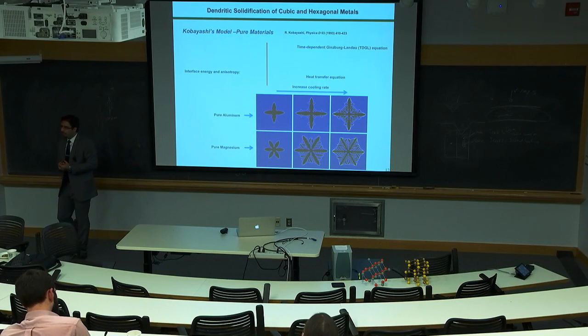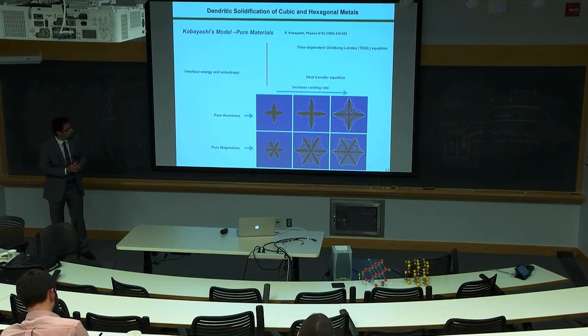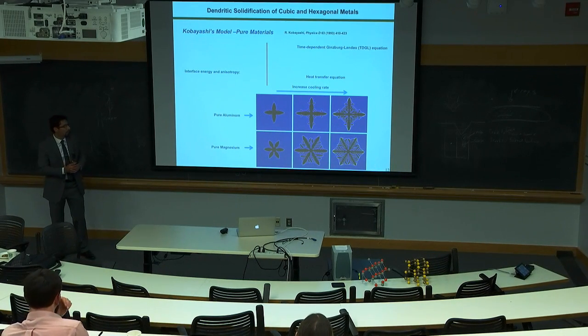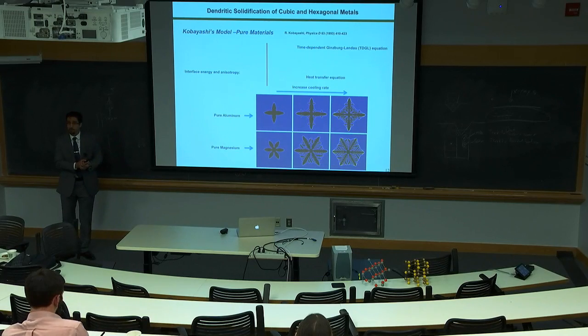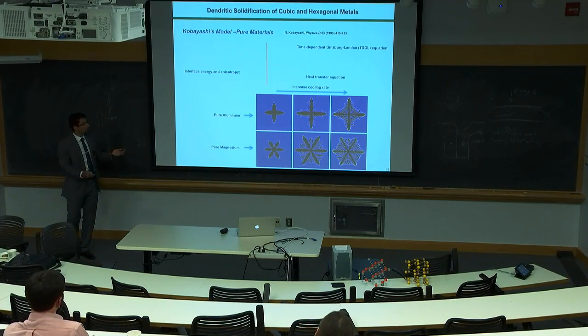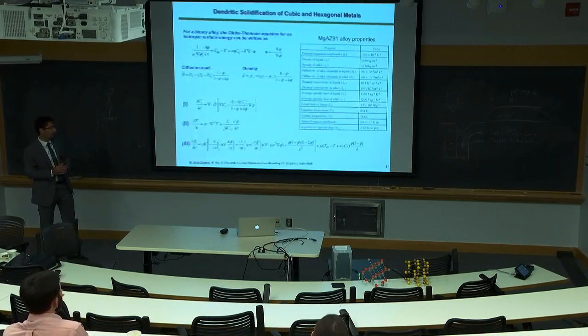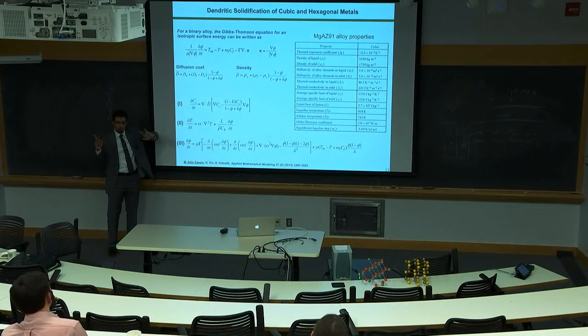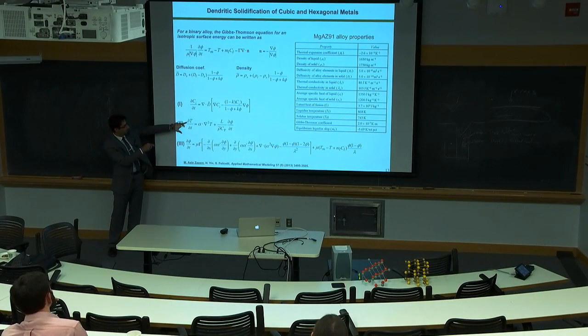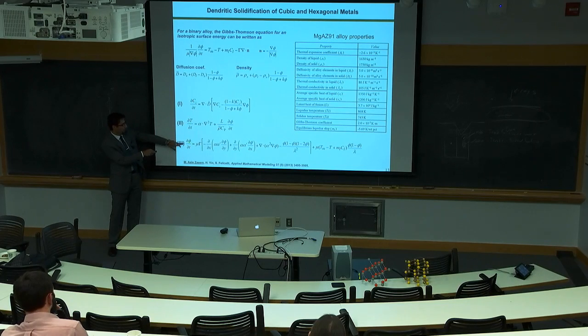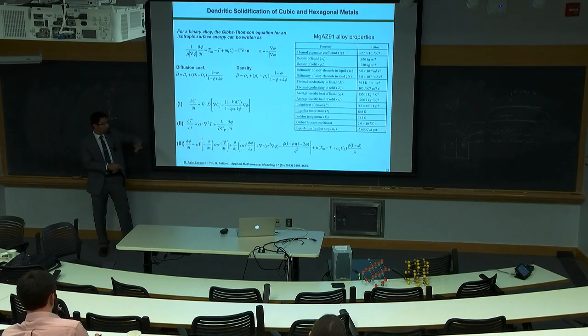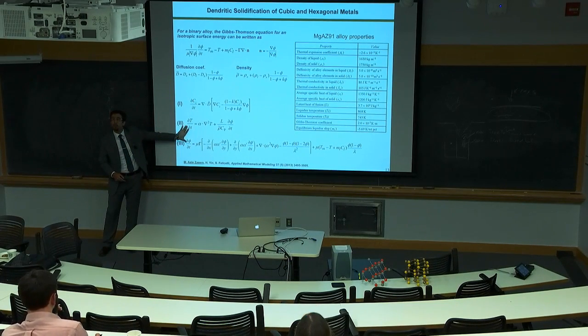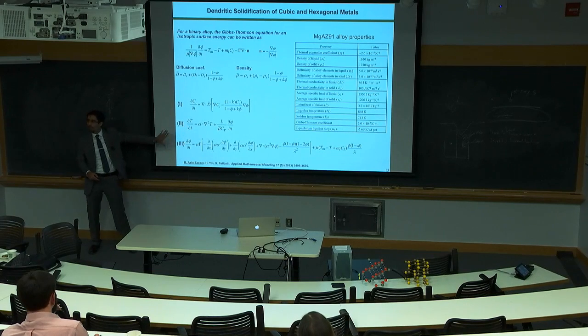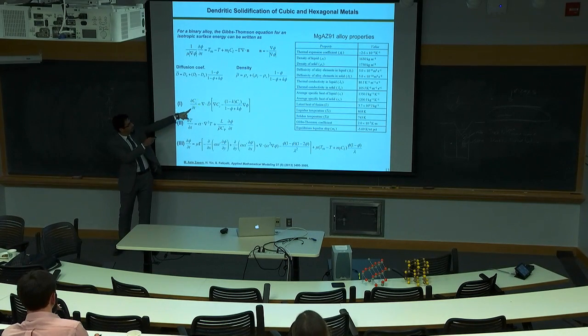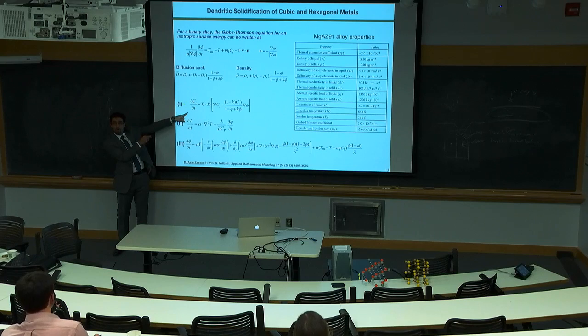In reality, in industry scale, we usually don't use pure materials. We use alloy systems, right? So what we did was we modified the governing equation. So let me say, those two equations are here. Temperature, heat transfer, phi, phase field. So these two are only good for pure material. But what if we have alloying elements coming? We need to have a diffusion type equation coupled to this, right?